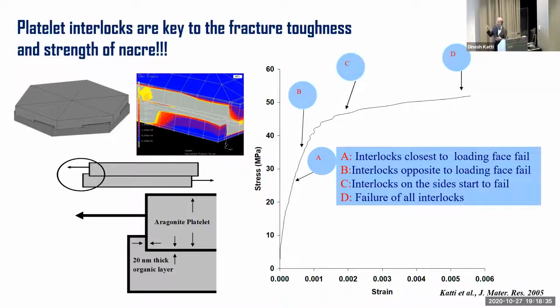So basically, what our work showed is that the platelet interlocks are key to the fracture toughness and strength of nacre. And that was an incredible result because people had been trying to find what's the reason for high fracture toughness, and we were able to find that, and we felt good about it.